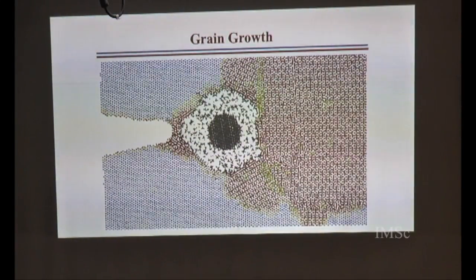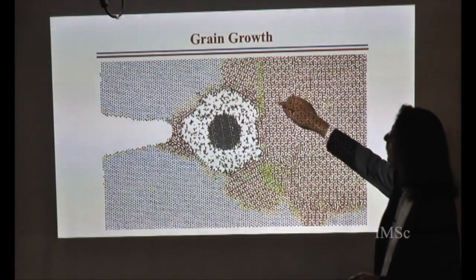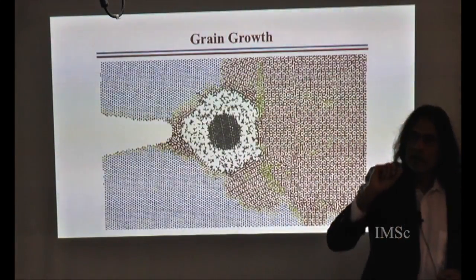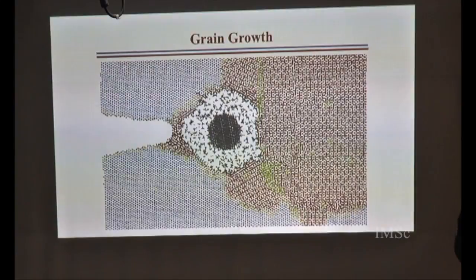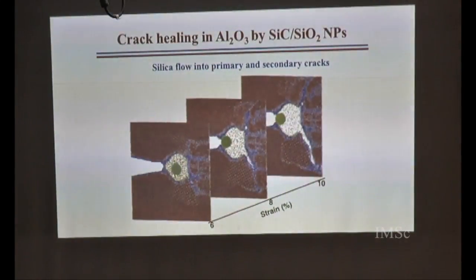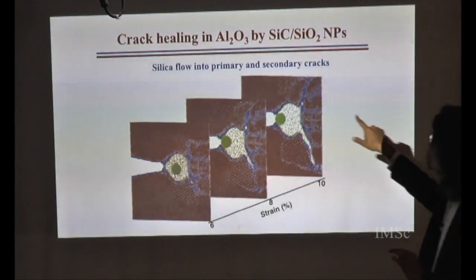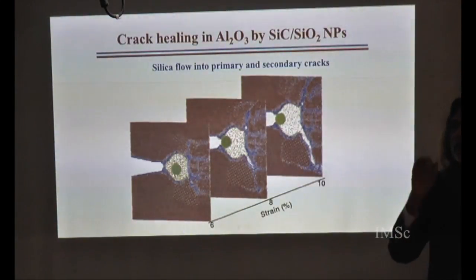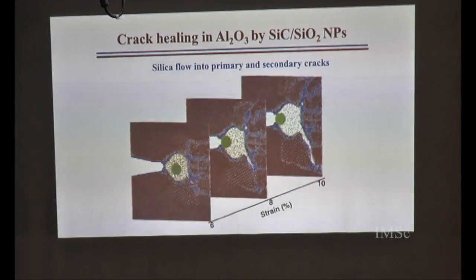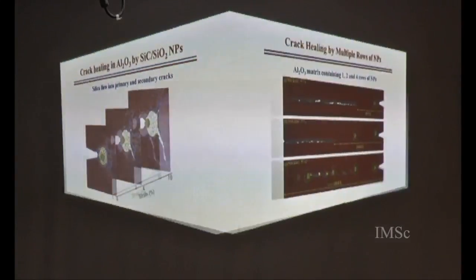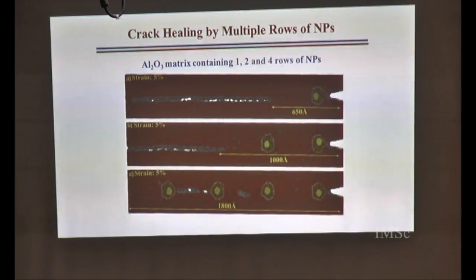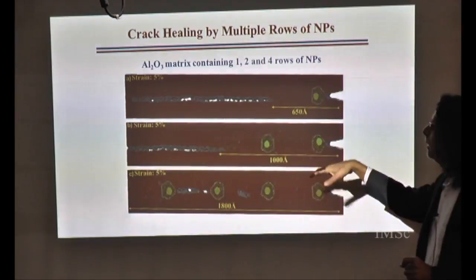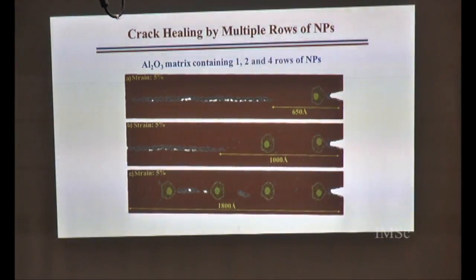Now, if you keep increasing the strain at these grain boundaries, you can begin to nucleate cracks. And what we find is that when that happens, silica flows into those secondary cracks also, and repairs them also. And so we have done this as a function of several particles, gone to very large strains and so on, and studied the nature of damage in these systems.